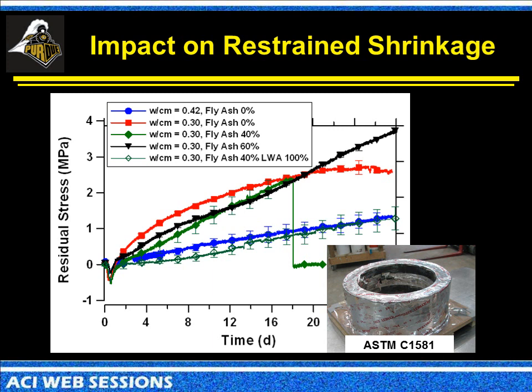Again, the shape of the curve is very important here because for the plain system, it comes up very quickly, and then as the reaction starts to cease because we don't have enough water in the system, we see this flattening out. With fly ash, though, we see this increasing and increasing, and we see that being a linear trend, so it's going up and up over time. Again, this is driven because we've got more autogenous shrinkage, more chemical shrinkage, in this case. The way we counteract this is through the internal curing water.